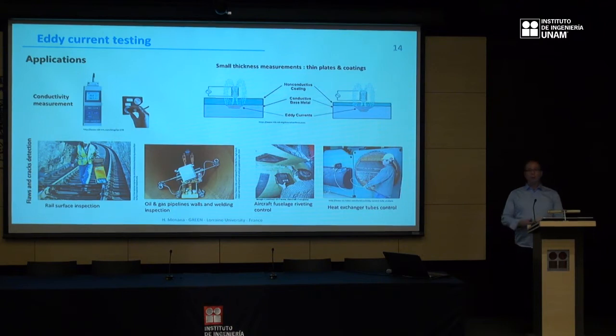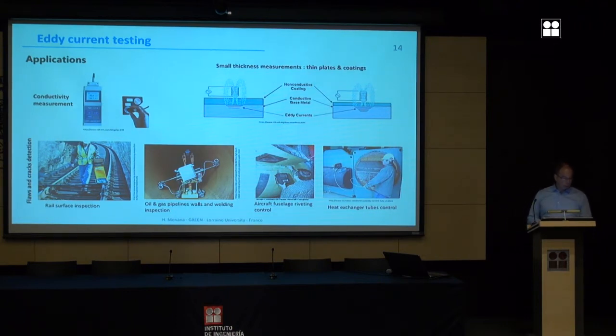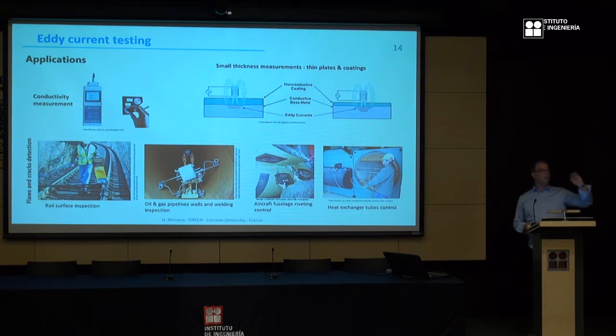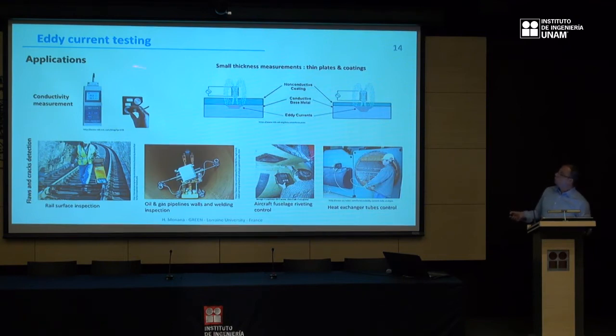There are many industrial applications of eddy current, like conductivity measurement, very small thickness measurement, or coat measurement. For coating measurement, the coat does not need to be conductive. If it's not conductive, it acts like a liftoff, and the liftoff influences the impedance variation of the coil. So we can measure a non-conductive coating on material.